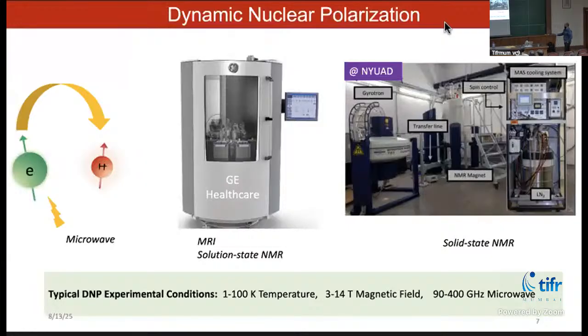So the temperature is about 1 to 100 Kelvin. Magnetic field is from 3 Tesla to 14 Tesla. And the microwave frequency that is needed is resonant with the magnetic field. So the range for this is from 90 gigahertz to 400 gigahertz. This is actually a challenge, like having a high power, high frequency source of microwave is a big challenge. So to create such microwave, one needs a special source. For the case of high field solid state DNP, we use gyrotrons for DNP.